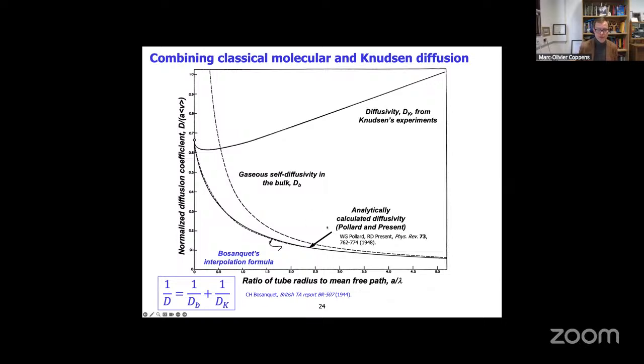And you have then an approximation derived by Bosanquet, which is extremely simple. It just says that you can add resistances. So instead of conductances, you have the resistance. The inverse of the diffusivity, in effect, an effective diffusivity at the pore level, is equal to the inverse of the bulk diffusivity, the molecular one, plus the inverse of the Knudsen diffusivity. And as you see, with this analytical formula, it has a really excellent agreement. And this was actually verified years later also with molecular simulation.